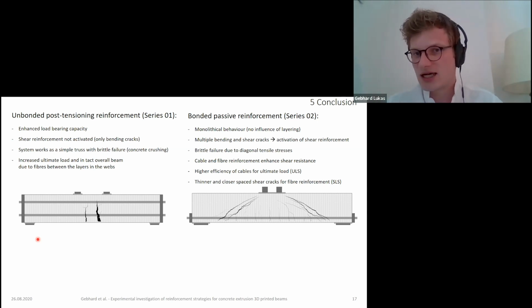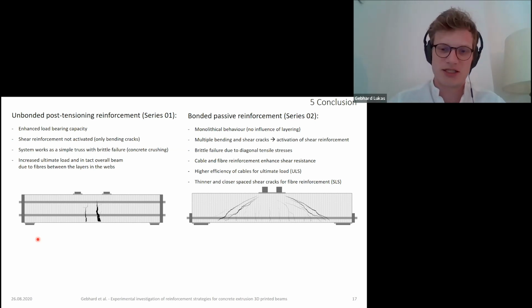The cables had a higher efficiency, so for cases where the ULS is decisive, this could be a good approach. However, for the cable, we still need to look closer at the bond between the cable and the concrete. And the fiber reinforcement was less effective than the cables. However, we had thinner and closer spaced cracks, which could be beneficial for some serviceability applications.